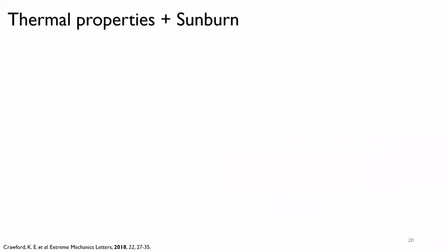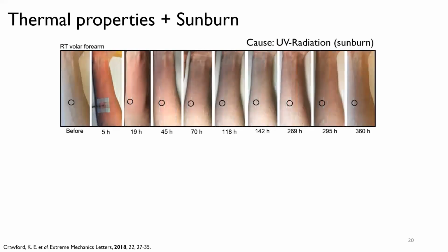So the next slide I'm going to show you is going to be a fast forward through over a year's worth of work. So all that hard toil that you do in your graduate lab and your graduate studies, I'm fast forwarding through some of that. And before we could put it on skin, we had to prove, does it actually measure thermal conductivity? We have to measure it on known surfaces, where we purchase standard materials that have very well characterized thermal conductivity, and then measure that. And then we do synthetic skins in different layers. We do high thermal conductivity, low thermal conductivity. How deep does it measure? How far out does it measure? So we had to do all of this background work before we could actually put it on skin, and then sunburn the skin as well. So we wanted to be really sure about our device.